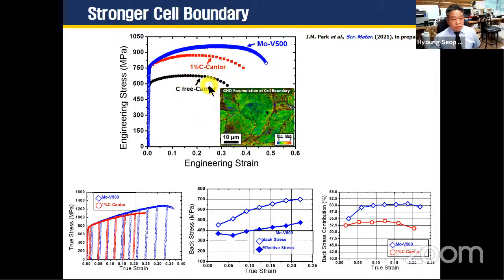So why is that good? In order to find the reason, we performed the LUR test, loading, unloading, reloading test, to measure the backstress. So we can measure backstress and forward stress, effective stress, like this. So backstress is the reason for the high heterodeformation induced strengthening. It's called HDI strengthening, due to the high backstress. The backstress is higher in molybdenum-added high entropy alloys than in the only carbon-added high entropy alloys.